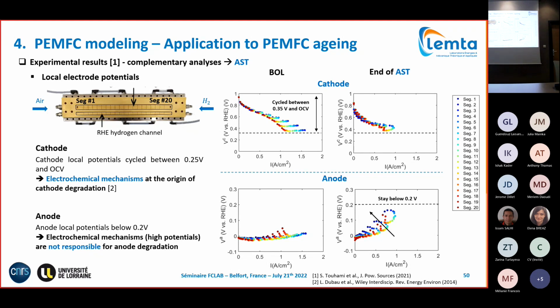I don't know if you can extrapolate to a stack. Because here, you actually used a linear cell. You rather use a linear cell inside the commercial PEMFC, and this was really to see why the linear cell, because it's easier to control, to ensure homogeneity of temperature, working conditions, and you really know that you will potentially have high concentration at the inlet, low concentration at the outlet. And what we observed at the beginning of life, we had a very homogeneous current profile, and at the end of life, something happened, and the heterogeneous current profile is actually at the origin of the heterogeneous potentials or vice versa. So something happened.